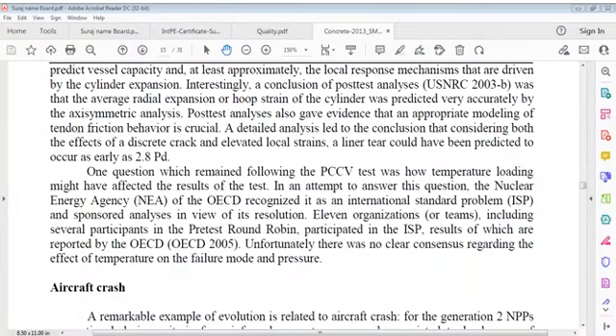Interestingly, a conclusion of the post-test analysis was that the average radial expansion, or hoop strain, of the cylinder was predicted very accurately by axisymmetric analysis. Axisymmetric post-test analysis also gave evidence that an appropriate modeling of tendon friction behavior is crucial. A detailed analysis led to the conclusion that, considering both effects of discrete cracks and elevated local strains, a liner tear could have been predicted to nearly occur as early as 2.8 PD.